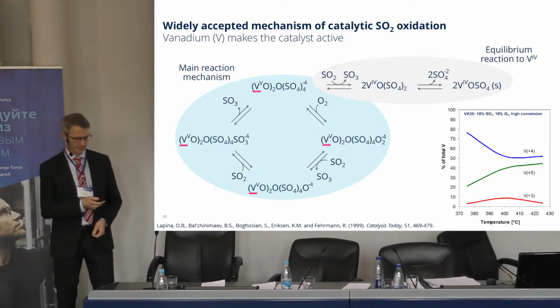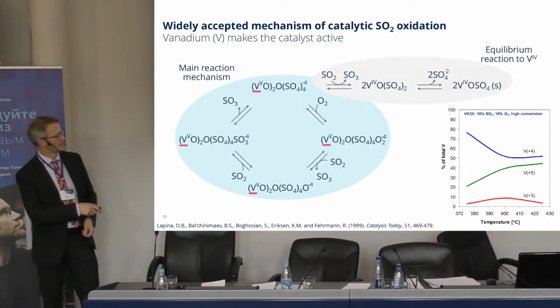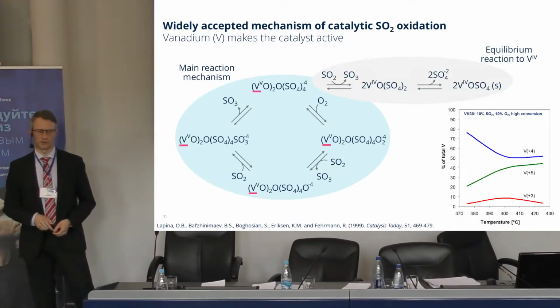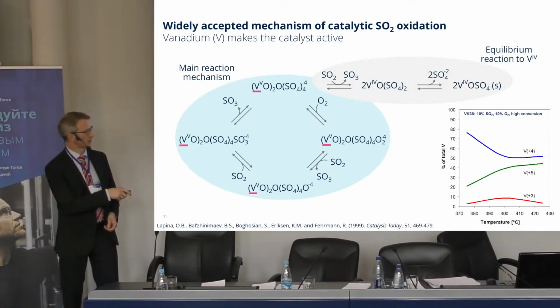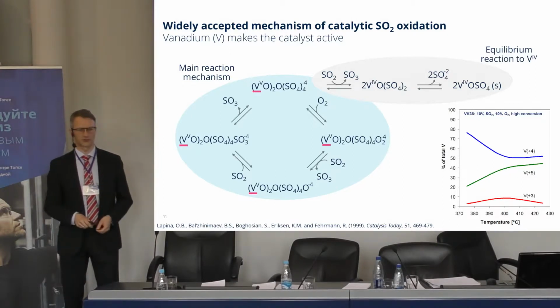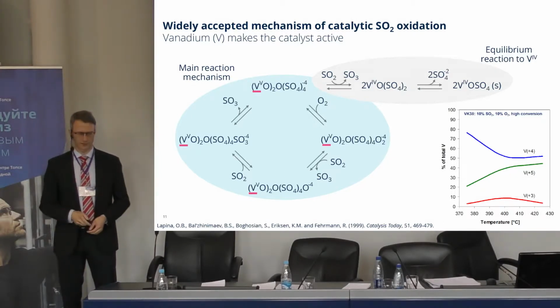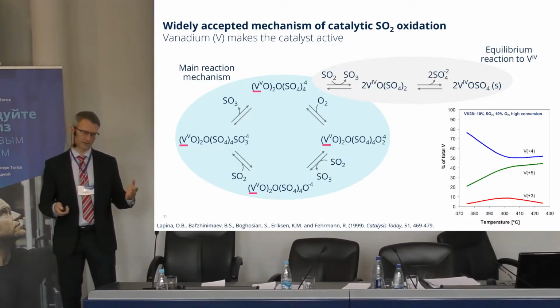It's not a deactivation as such, but an equilibrium that adjusts for a particular catalyst system and operating conditions. At some point, we did experiments where we quench-cooled the catalyst directly from operating conditions, and then afterwards we measured the oxidation states. We found that, depending on temperature, quite a lot of the vanadium was vanadium 4, and of course also quite a lot of vanadium 5, but certainly part of the vanadium is in the state 4. So one of the challenges for this catalyst is to maximize the content of vanadium 5 in the catalyst.